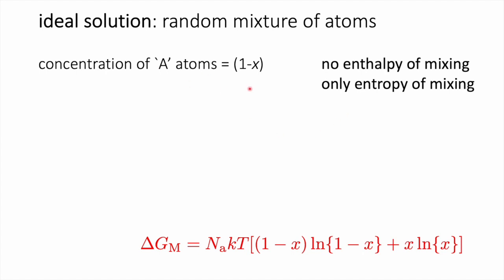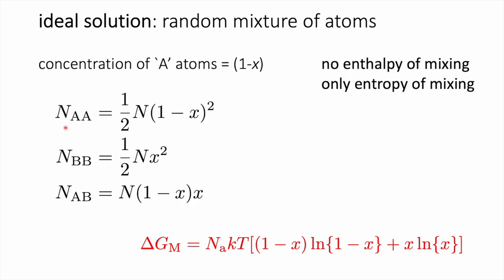So if the concentration of A atoms is 1 minus X, then the chance of finding an A atom is also 1 minus X. And if we consider the number of AA pairs in our random mixture, then that will be equal to the chance of finding an A atom, which is 1 minus X, multiplied by the chance of finding another A atom, which is also 1 minus X, and therefore we have 1 minus X squared, the number of atoms, and we divide by 2 because we can't distinguish the first A and the second A from the second A and the first A atoms. Okay, so the number of AA pairs is simply half N into 1 minus X squared.